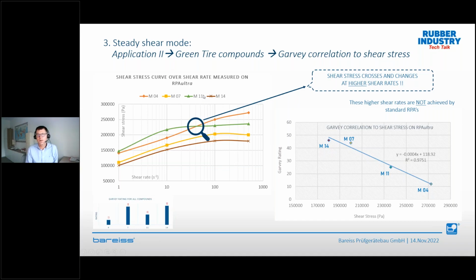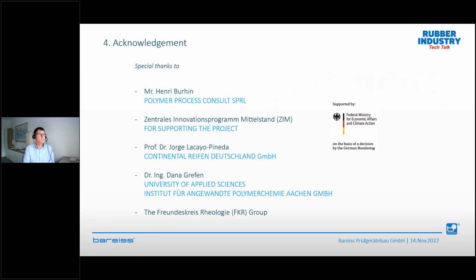And that is something where a lot of people are very excited now, and we are going on with a lot of tests which are planned. This is what I wanted to discuss and present today. For sure, all dynamic tests are important to give you information about polymer structure, molecular weight distribution, and long-chain branching. But if you really would like information about the processing behavior, you need to go to a steady shear mode. The RPA Ultra is really able to perform both dynamic tests and processability tests.